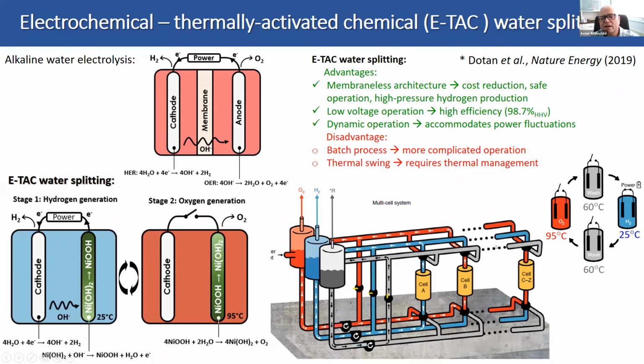In real life, that is a scheme of the process without moving the electrode from cell to cell. Of course, that's for lab proof of concept, but in reality, we do this in a multi-cell system where every cell is connected to 3 water or electrolyte reservoirs. One is kept at high temperature, and that is the oxygen-rich electrolyte. One is kept at low temperature, that is the hydrogen-rich electrolyte. And we also introduce an intermediate temperature electrolyte to wash the cells from one stage to the other.